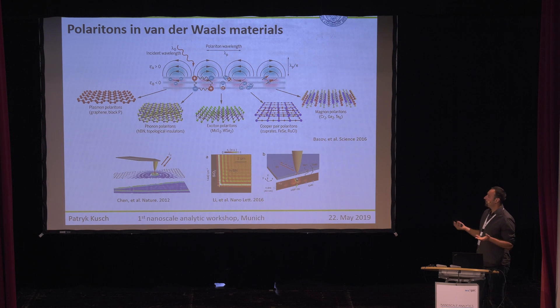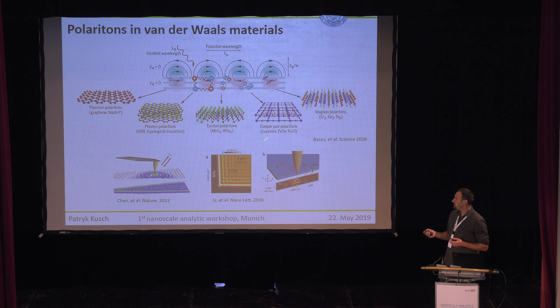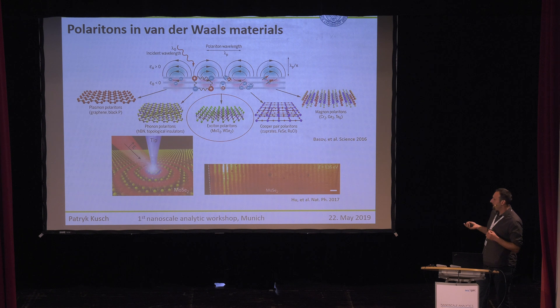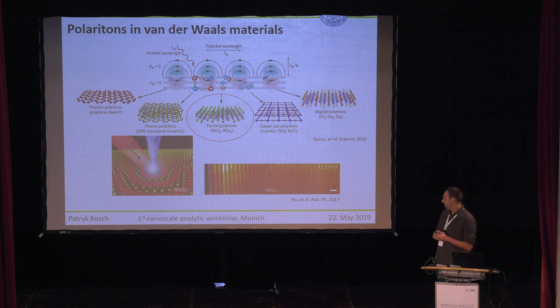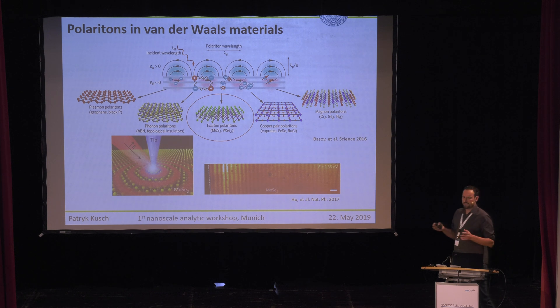Harvey told a lot about polaritons — plasmon polaritons and phonon polaritons — so I don't have to introduce them. We think about why we should care about the visible, and it's because of MoS2 and tungsten diselenide. Here we have excitons with huge binding energy that can be excited in the visible range and have very long lifetime. The first results of how such exciton polaritons can be visualized are by Yu et al. — traveling waveguided exciton polaritons inside molybdenum diselenide over a really long distance, above 12 micrometres, at an energy of 1.35 eV. From the Raman spectroscopy point of view, this is already infrared.